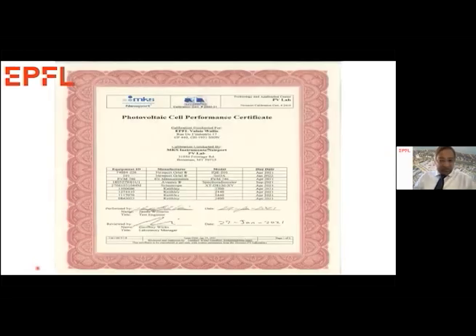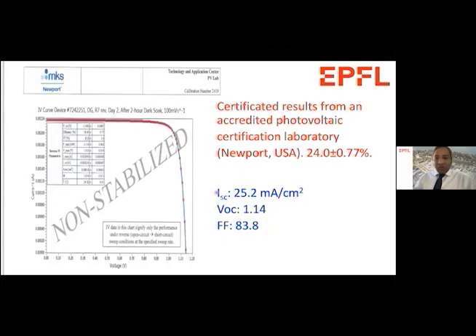We sent these solar cells to Newport for certification, and they measured an efficiency of 24 plus or minus 0.77. So this is the certified data coming from Newport in the States, and the previous data was measured in our lab, so our data is consistent. If you look at the VOC and the current, the current is 25 milliamps, as I mentioned before, the VOC is very close, 1.14, and the fill factor is 83.8. So this way we get very good efficiencies measured at Newport.